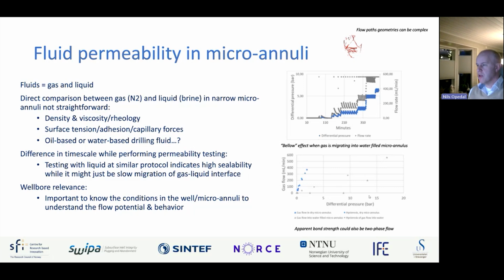So either you have a gas breakthrough, or you have a microannulus that was there, but the test essentially just shows that the water is being squeezed out of the small microannulus. The example on the top right is a bit small, but in red, sometimes the flow path geometries can be quite complex. So the wellbore relevance of what we take away is that it's important to know the conditions in a well or microannulus to understand the flow potential and the behavior.